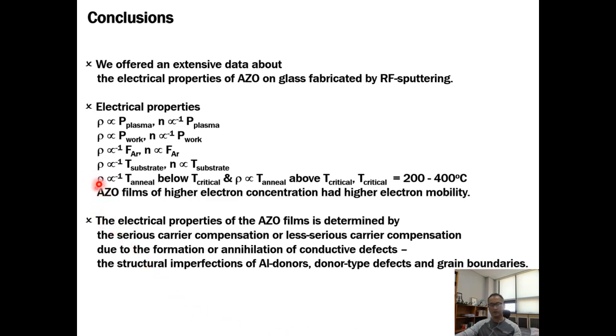Electrical resistivity decreased with annealing temperature until a critical temperature, and after that electrical resistivity increased. The critical temperature is about 200 to 400 degrees centigrade. Electron concentration is vice versa. AZO films of high electron concentration had high electron mobility.